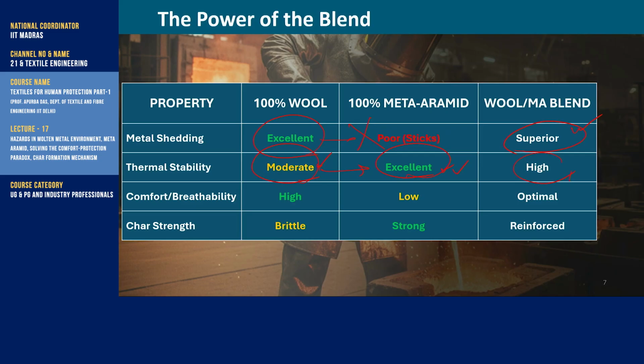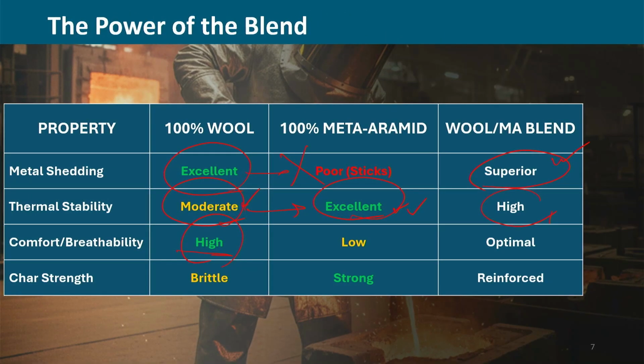Comfort and breathability: for wool it is excellent, we get very good comfort and breathability from wool. Why have we said comfort and breathability is high, not excellent? Because our target was to use a little bit coarser wool, okay. So the comfort level is a little bit reduced, but it is much higher than the aramid fiber. Aramid is low. So, if we blend we will get optimum comfort, which is the minimum requirement. So, we are getting superior metal shedding, high thermal stability and the optimum comfort and breathability that we are achieving.